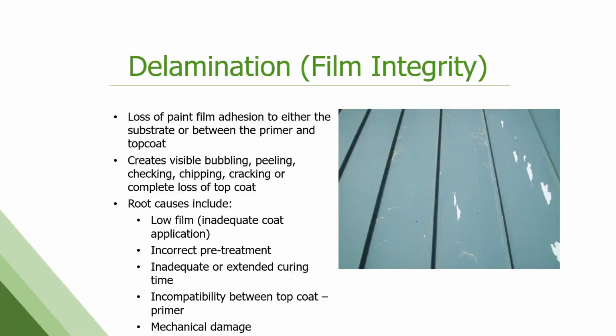So that would be the coater not having applied the right amount of paint to the surface. An incorrect pre-treatment, so you don't get a good bond of the paint to the substrate. Inadequate curing of the paint system. Some kind of incompatibility between the top coat and the primer. We've seen that where the, quote, wrong primer was used under a top coat, so there's not a good bond.